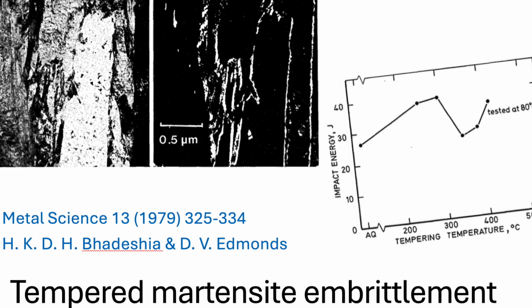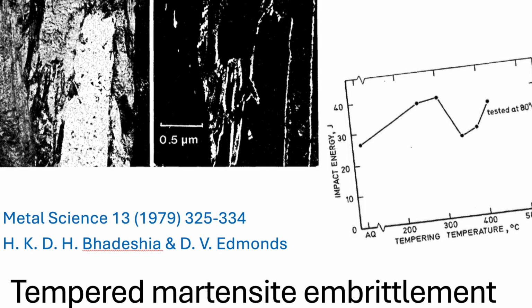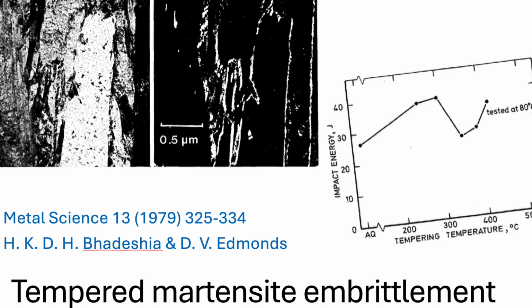Okay, let's zoom back in then. We know this retained austenite, the RA, is unstable, and it sits in those thin films between the martensite laths. What happens to that RA when the steel hits that critical 300-degree temperature range? Right. This is where the real detective work happens, using transmission electron microscopy, TEM. That was the heroic tool in this research, allowing them to see these tiny structures.